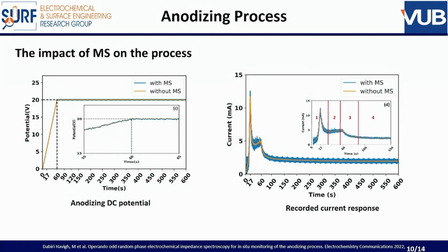So here you see, for example, anodizing, which was studied largely by George Thompson. In fact, what we do here is apply the classical anodizing process that, for example, companies like Airbus are doing. And on top of that, we sample our impedance measurements. This is the current response, and you see the current response is the same with the multisine and without the multisine. And out of that, we can recalculate the instantaneous impedance and follow the impedance as a function of, for example, in this case, the oxide film formation.